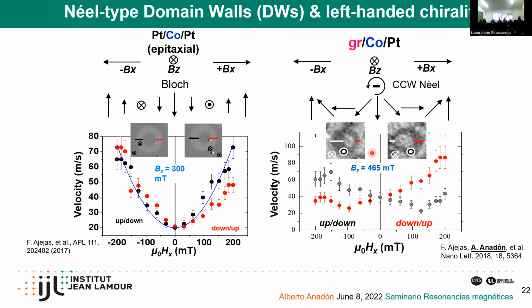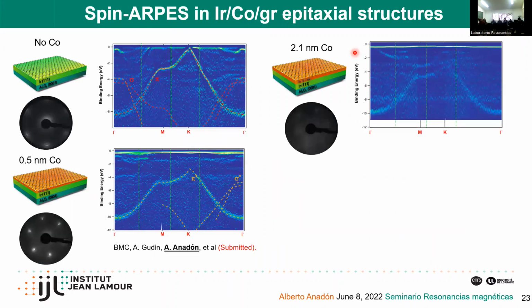Basically, we are able to compute how much is the Dzyaloshinskii-Moriya interaction in the graphene cobalt interface, and it is within the same order of magnitude as the one that we can see in the cobalt platinum interface. And this is very interesting because in principle, graphene is very weak in terms of spin orbit coupling. So what's happening here should come from the graphene cobalt interaction, or the graphene cobalt interface, and not from graphene itself. So what we did with these samples was to study this interface. We took these samples to the synchrotron, and we were able to measure in more detail the photoemission spectroscopy with angle resolved and spin resolved bands. So basically, we measured the bands.